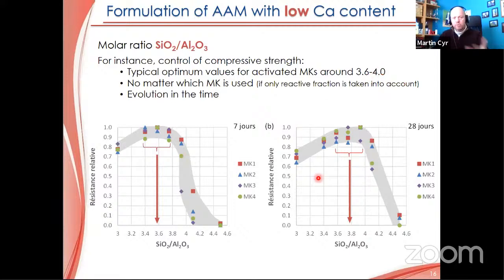And it's quite easy to find this kind of thing when we are trying to make the formulation of the material itself. And here, what is interesting is that no matter which metakaolin is used, it is working quite well. But you have to use only the reactive fraction of the metakaolin itself, not count the quartz inside, not count the mullite inside. So you have to take care of the characterization of the precursor itself. So I quite agree with what was said earlier about this. So this molar ratio is very interesting.